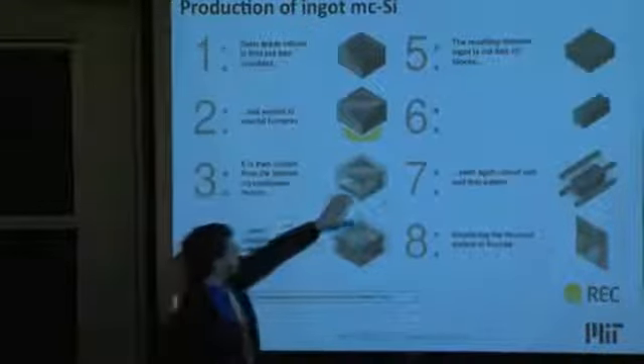So you put your solar-grade silicon into a crucible, and then you melt the silicon inside of it. Silicon melts at 1414 degrees Celsius. It's a very high temperature. So 1,414 degrees Celsius is the melting temperature of silicon. And then it's cooled, not just randomly, but from the bottom up.